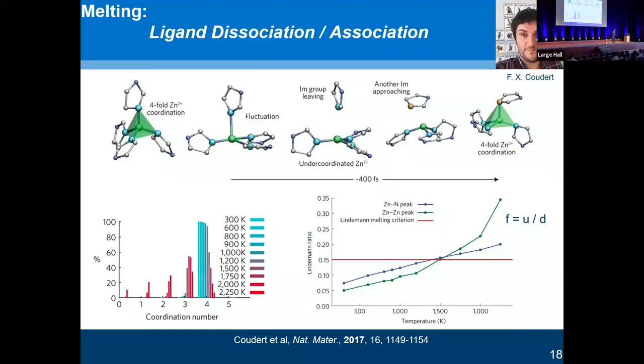How does all of that melting happen? What is the mechanism of thermal collapse? Well, that's known through FX's great work in 2017, where we're heating a system. The weakest bond, in this case, the zinc imidazole bond, breaks at high temperature, and then it's replaced by another one coming in.